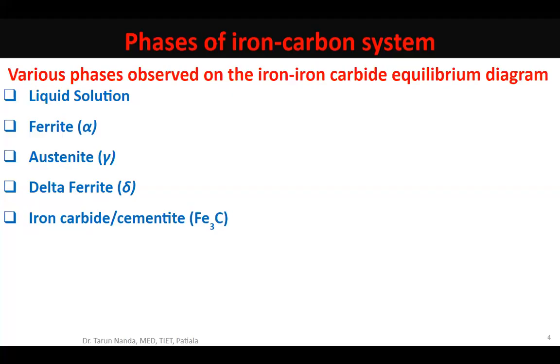1147 degrees centigrade. Even at a temperature of 727, the solubility of carbon in austenite, or in gamma iron, is huge. It's 0.77 percentage carbon. The conclusion to be drawn is that the carbon solubility in austenite is significantly greater than it was in ferrite, or it would be in delta ferrite, which we'll discuss just after a while. Coming to its crystal structure, the solvent's crystal structure is FCC, gamma iron is FCC. So austenite, a solid solution of carbon in gamma iron, is also FCC.